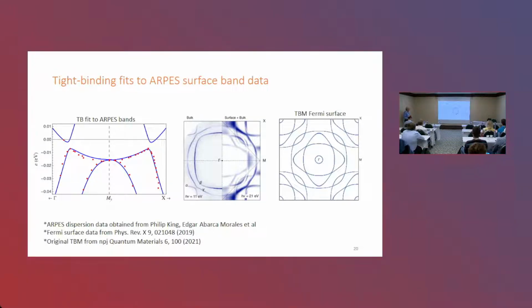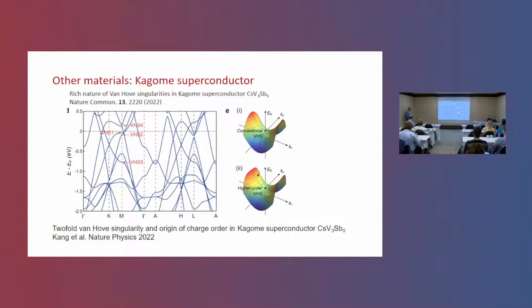Moreover, using quasi-particle interference from the tight binding model, with very good precision, we can reproduce for free the Fermi surface, which is close to the experimental one. So this is very, very close to getting the solution whether there is a higher order Van Hove singularity here.